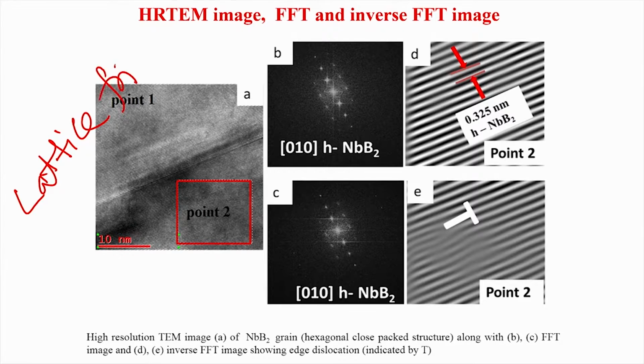So, transmission electron microscopy analysis of ceramic materials like niobium boride is extremely difficult, because the sample preparation itself takes a lot of time, as one needs to have that electron transparent thin film before one can get decent, reasonable and scientifically meaningful transmission electron microscopic images. Now, this left one, if you see, is the bright field TEM image of niobium boride, and one can clearly see these lattice fringes, right.